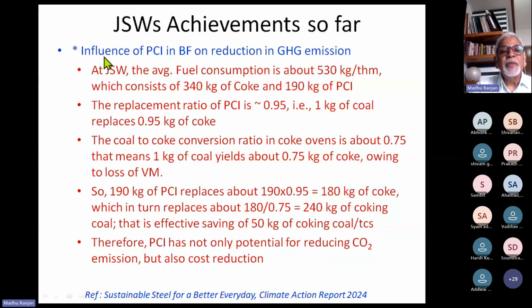So if we want to see how PCI introduction in blast furnace has an effect of reduction in greenhouse gases, the JSW figure that I have obtained is that their total fuel consumption is 530 kgs per ton of hot metal, and this consists of about 340 kg of coke and 190 kg of pulverized coal injection. They have also found that the pulverized coal injection has a replacement ratio of 0.95. That is, if you charge 1 kg of coal, 0.95 kg of coke is reduced.